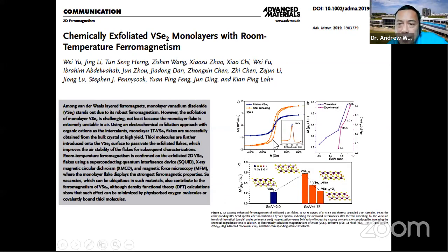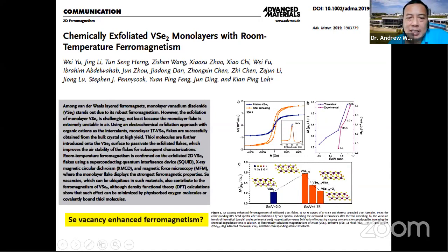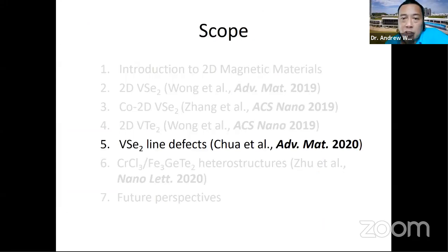And they did further studies to study the magnetism of this material, which is full of defects. If they saturated the defects, so sorry, they did some calculations. So this shows that if the defect concentration increased, it becomes more magnetic. But if they saturate it with thiols or oxygen, it becomes less magnetic. So it suggests that defects have got something to do with the magnetism. So building on this, we continued this study on defects to understand why some people measure magnetism in vanadium diselenide.